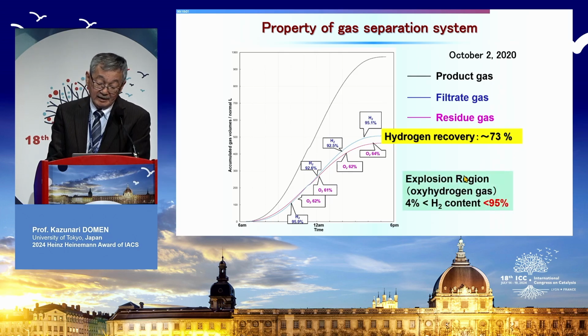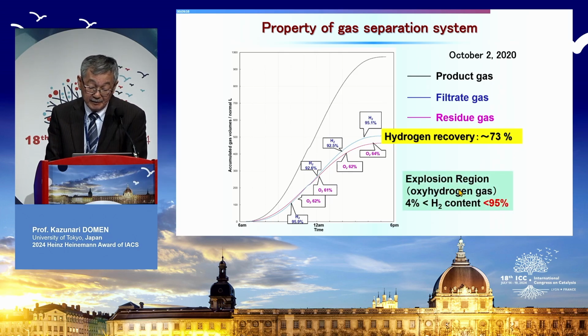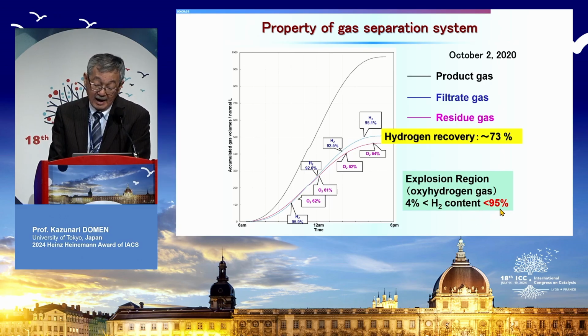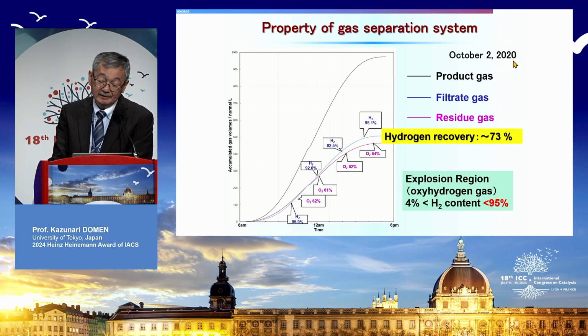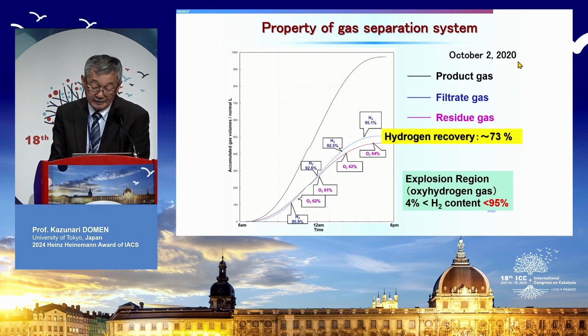And as you know well, the explosion region of oxygen-hydrogen mixture is very wide. To avoid this explosion region on the hydrogen-rich side, we need to obtain more than 95% purity. However, in this particular experiment, in the daytime, our mixture is still inside of this explosion region. But this experiment was carried out in 2020. So at present, we continuously obtain more than 96 to 98% purity.